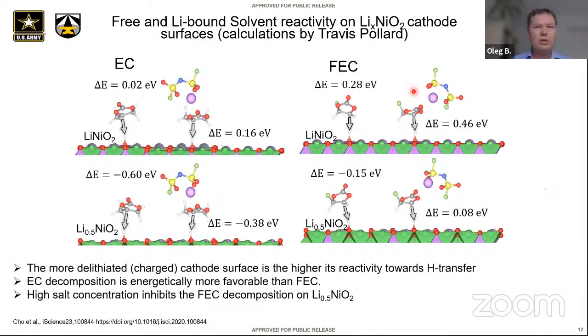And this picture which Travis has created, I think is a very elegant view of major trends. So we are going to take a fully lithiated nickel oxide, very aggressive, and start with EC. EC on a fully lithiated surface has an essentially isoenergetic H transfer reaction, right? Once we now remove some lithium, which occurs during charging of the battery, then this energy becomes very largely negative. And the more you charge, the more reactive your surface becomes, right? So that's the idea for, well, that's when you start limiting charging if you cannot get rid of all the protons, or there might be some other methodologies, right? So that's a clear trend.